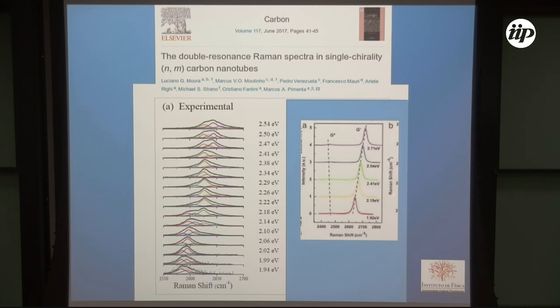And this is the 2D band. In graphene, it is a very symmetric Lorentzian band. And in carbon nanotubes, we see some similar aspects, but not exactly the same. We don't have one single symmetric band. We have several sub-peaks, clearly. If you look, for instance, at this red sub-peak, this red sub-peak is not dispersive, but in a way, the average behavior of the bands is dispersive. Okay? So it's similar, but there are some important differences.